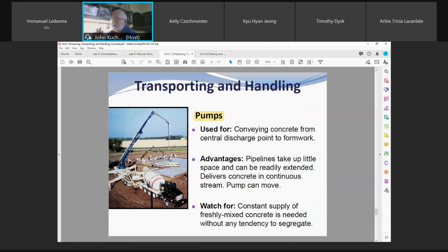Where does the air go? You don't lose it. And Tyler Lay, and I'll send you guys that video, he's got a great video that I've sent to a lot of the other testing agencies to look at. And he made a research study on it. And he just says, you don't lose air. It's there. It's going to be in the forms after. But yet, when you do your air concrete test at the end of the pump, and you need 5 to 7, and for some reason you're showing 4.5, you've got it. It's in there. It'll come back. Okay? Temperature, bubbles, dissolving. Is that the air entrainment videos?